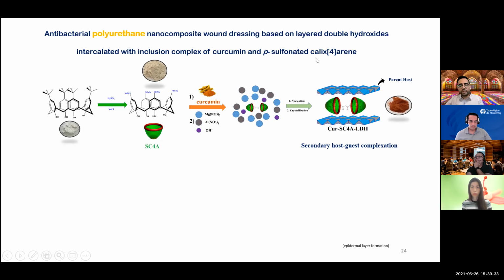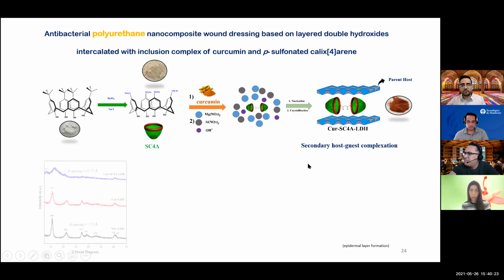First of all, we use sulfonated calixarene. It's this shape, as you can see, it has a basket shape. We can use this one, and we can put the curcumin in it. And after that, curcumin can insert inside of this basket as a primary host. After that, as an in situ production, we can produce some LDH nanoparticles, the layered double hydroxides nanoparticles. And the thing is that we want to intercalate and send this primary host with curcumin between the layers of the LDH, so LDH can protect against some isocyanate groups and other things like that. So it's known as a secondary host-guest complexation.